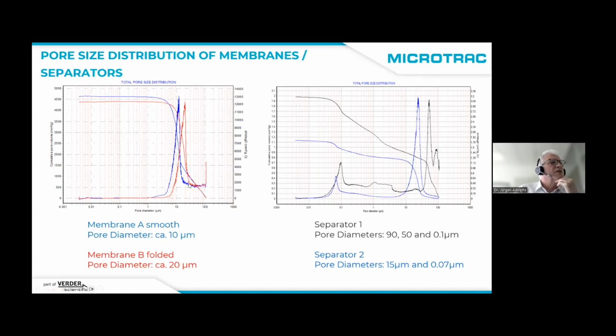So we do have here an example for a smooth membrane with pore diameters in the range of 10 microns. If it's a folded one, here, for example, we found 20. In another example, we have a separator. The one is characterized by 3 pore sizes, in the range of 90, 50, and 0.1 micrometers. And the blue one here is another separator with pore sizes in the range of 15 to 0.07 micrometers.